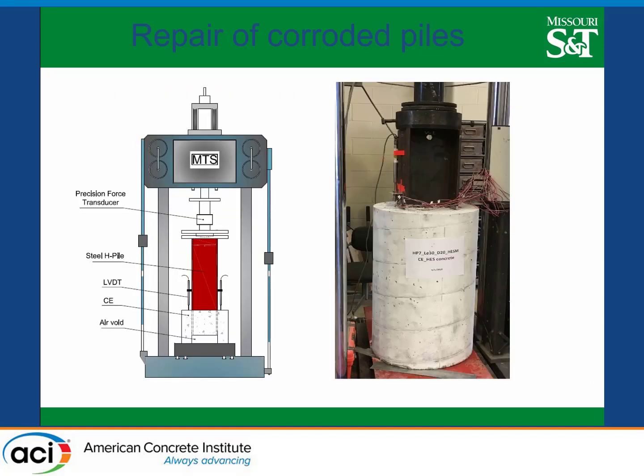So we start by looking at what the friction and cohesion is between the concrete and the steel piles. On the concrete side, we looked at different sorts of concrete: conventional concrete, high early strength, UHPC, polymer modified concrete, and geopolymer concrete, thermal cured and ambient cured. So we looked at 6 or 7 different types of concrete. For each one, we have the steel pile extending all the way over here, and a 2-inch gap, and then we push the steel pile versus the concrete, and based on this you come up with a slip versus stress curve for the different types of concrete.